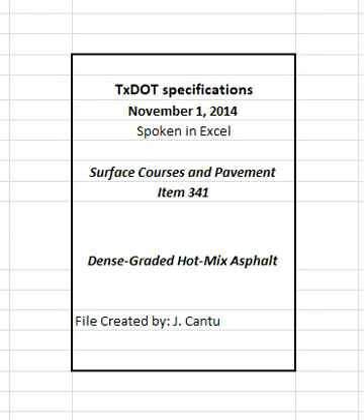4.7.3.1.1 Thermal segregation. 4.7.3.1.1.1 Moderate. Any areas that have a temperature differential greater than 25 degrees Fahrenheit, but not exceeding 50 degrees Fahrenheit, are deemed as having moderate thermal segregation.